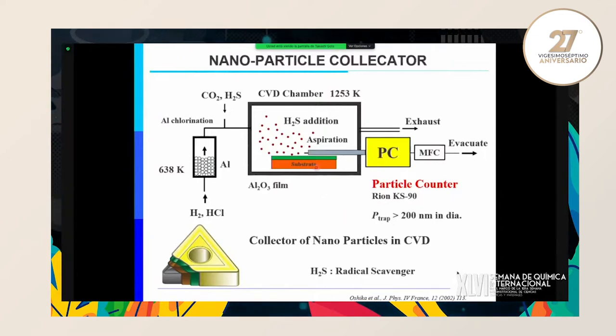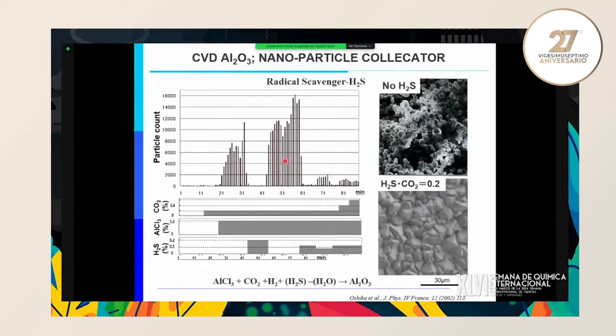And if we add hydrogen sulfide to the source gas, nanoparticles can disappear. So H2S is called a radical scavenger. This is how nanoparticles form. If you do not add H2S to the source gas, the alumina film is just agglomerated powder particles. If you add hydrogen sulfide to the source gas, the alpha alumina film becomes a very fine, faceted, well crystallized film.